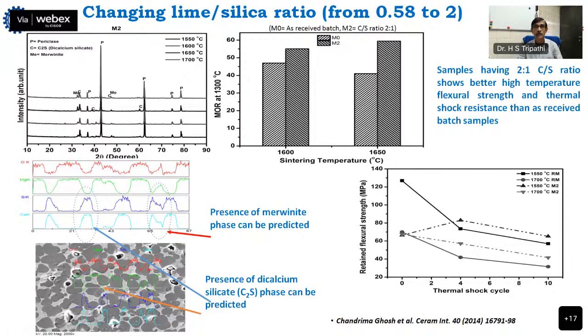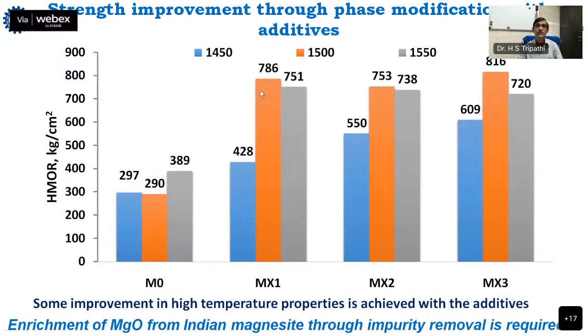And the same thing, the flexural strength can also be improved, but we cannot improve the MgO content without any beneficiation. Same thing, if we use some typical additives to combine this lime, so that it can form high melting phases, then also we can improve the property. This is the as-received magnesite sintered at different temperatures, 1450, 1500, 1550 degrees centigrade. If you use 1%, 2%, 3% additives, we can see the additives also change the phase assemblage.